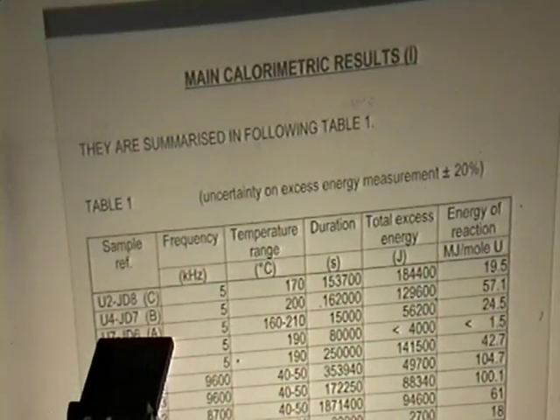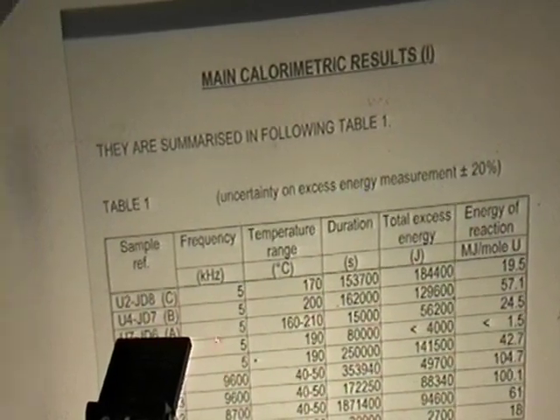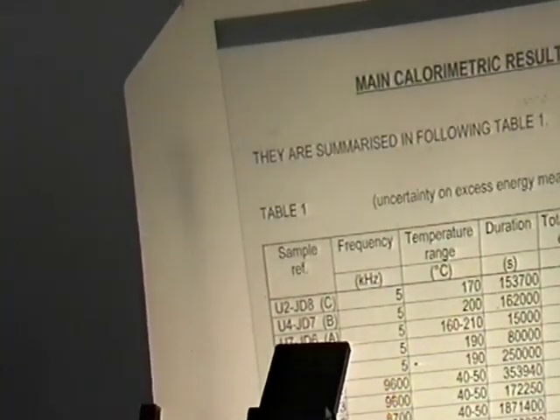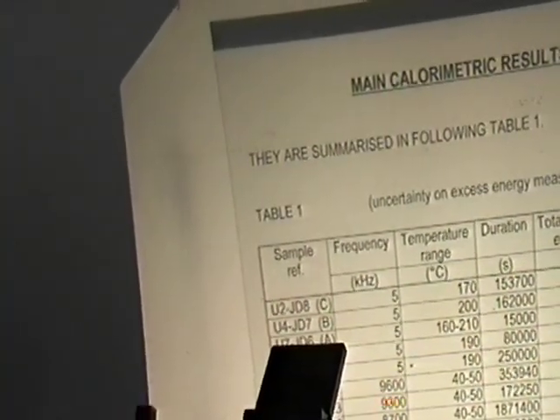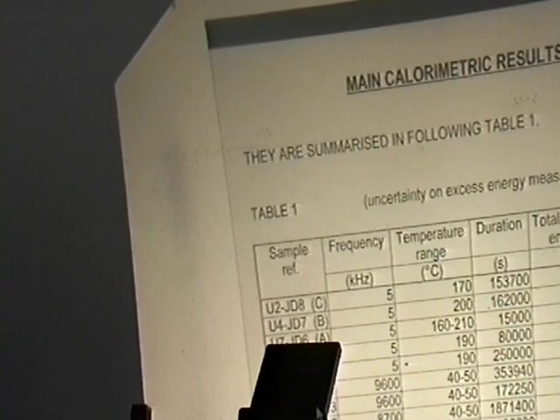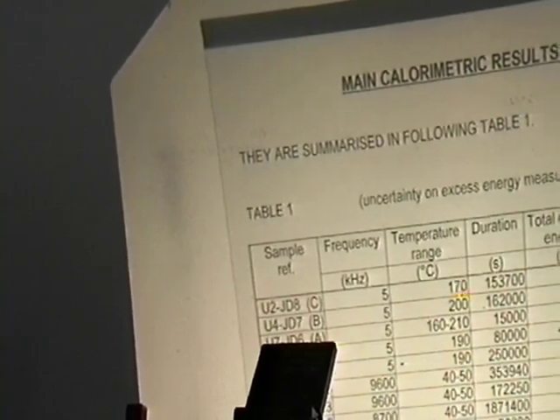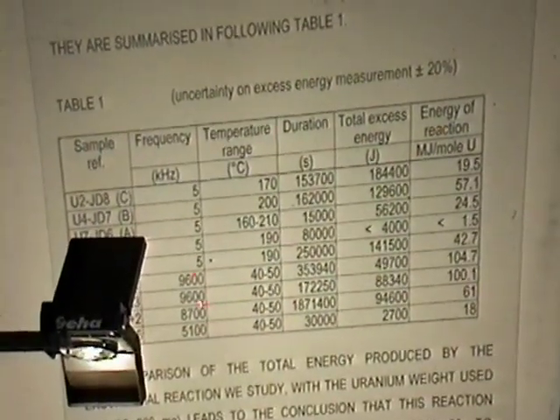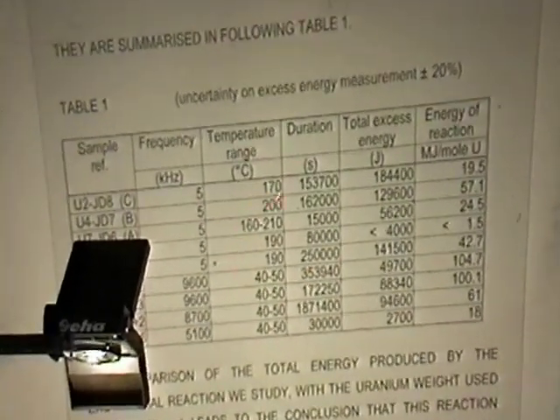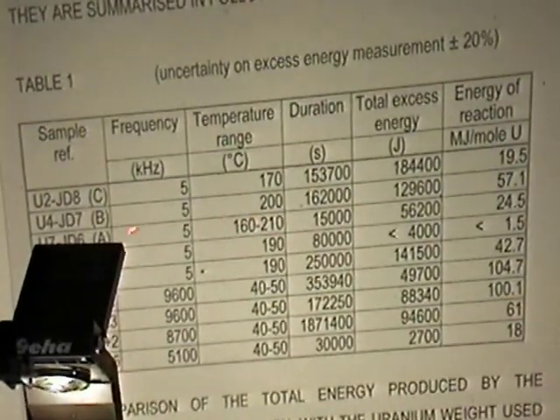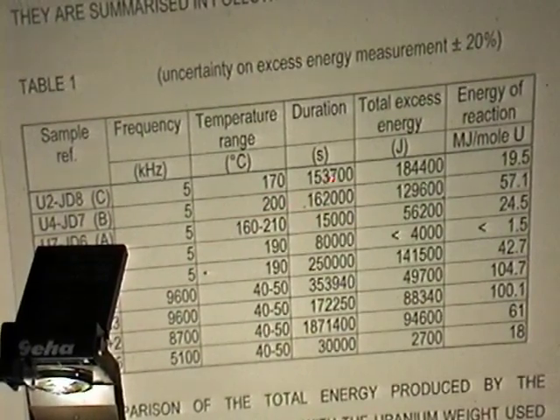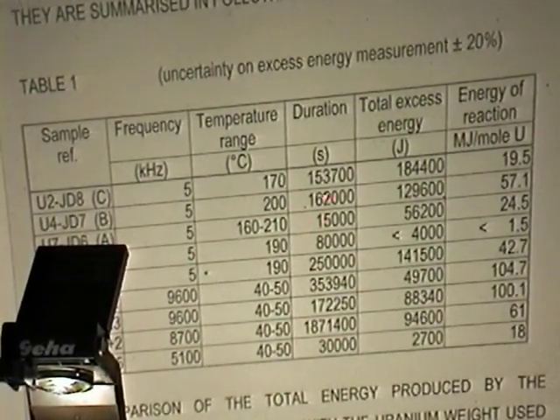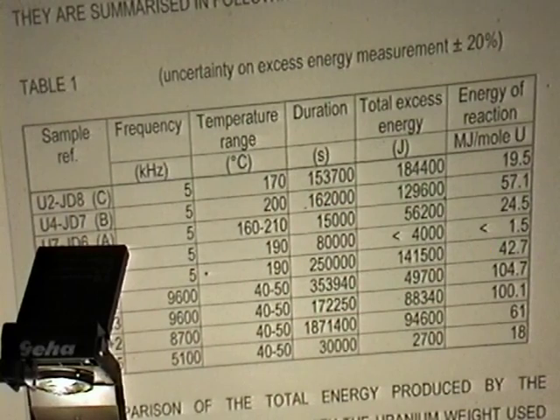So this is a summary of the main calorimetric result. You can see here the frequency, so you have 5 experiments with 5 and 4 with 9 megahertz, and this is 5 kilohertz. And you can see here the temperature range. You can note that the temperature range for megahertz experiments is lower than the range for lower frequency experiments. The duration was in the order of 100 to 1 million seconds.